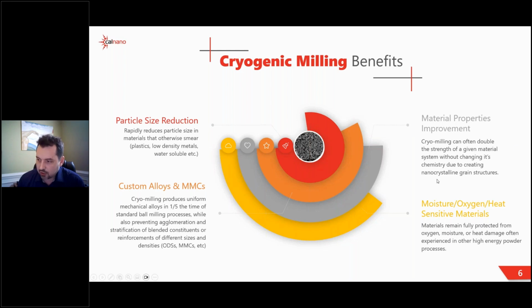The traditional application that we were actually founded on was really for the purpose of enhancing the material strength. So as one example, we took 6061 aluminum alloy, very common, and we were able to double its strength by just reducing the grain size. So while we're cryogenically milling, the impact locations between those grinding media essentially act like a forging, where every little particle is going to get forged, reducing the grain size of the material.